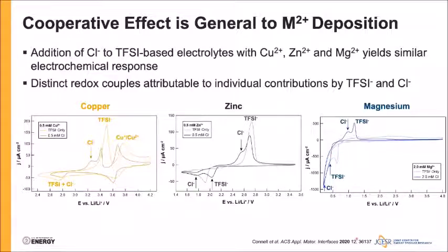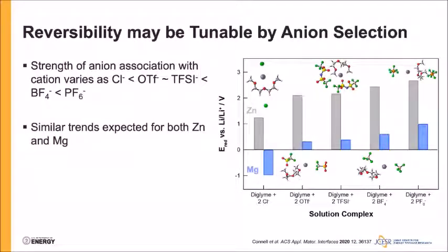We'd also like to know, again, I made the point at the beginning of my talk, can we mimic what chloride is doing? Does this effect extend to other anions? And so to understand what trends we might expect, we turn again to DFT, and we see that as we start to play around with anions of differing association strengths, we do see a consistent trend of a shift in the redox potentials. We move from more strongly associating anions like chloride to very weakly associating anions like PF6. And we expect very similar trends for both zinc and magnesium.